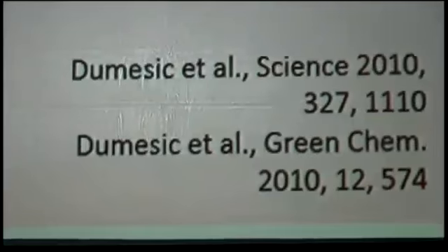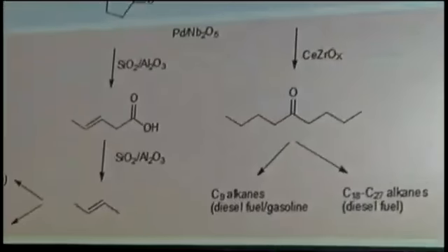Dumesic also showed that there are nice things to do with pentanoic and pentenoic acid, converting it via different kinds of chemistry to all different kinds of fuel ranges. The key step here is going from gamma-valerolactone to pentanoic acid. What both the Blanche group and the Dumesic group use for this is a bifunctional catalyst where you have a metal hydrogenation function as well as a strong acid, and the strong acid is required to ring open the GVL to pentanoic acid. The steps after that, hydrogenation of pentanoic acid, are actually quite straightforward.